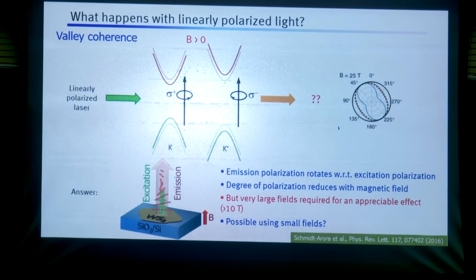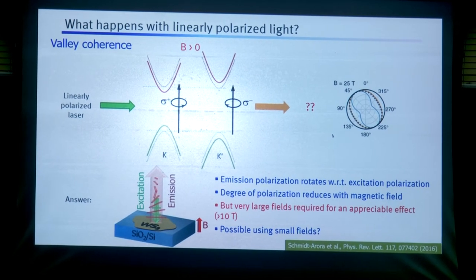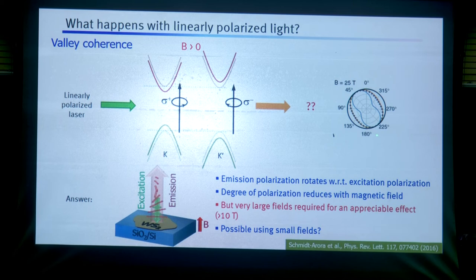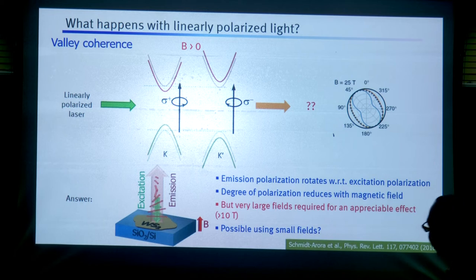I will just give you a short answer from this paper. The answer is that the emission polarization rotates with respect to the original excitation polarization. So the two valleys have a phase difference. It's similar to, let's say, the Kerr effect, where you have a rotation of the plane of polarization when you have created a phase difference. But here you have created the phase difference in the two valleys by changing their energies, and this phase difference appears in the emission process and not in reflection or transmission, which was the Kerr or Faraday effect. This is emission. So here the valleys are emitting as a superimposed state, but with different phase now. So we have controlled phase.